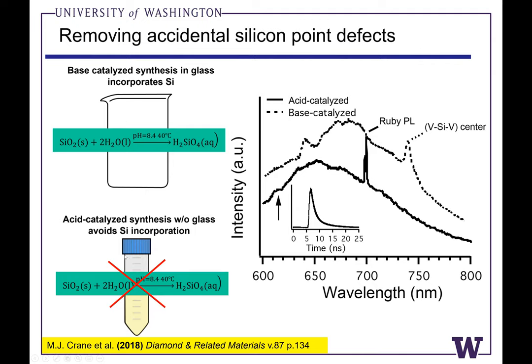So we did a control experiment with a glass-free reaction vessel. This is just a plastic Falcon tube. And we could still use the base catalyzed reaction or acid catalyzed reaction, but when we switched to a plastic reaction vessel, we hypothesized we would no longer make silicic acid during the cross-linking reaction. And sure enough, that's what happened.